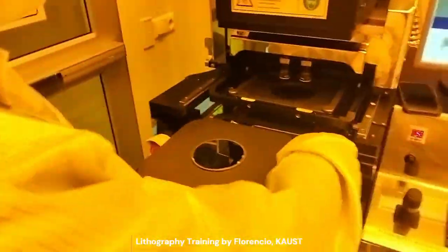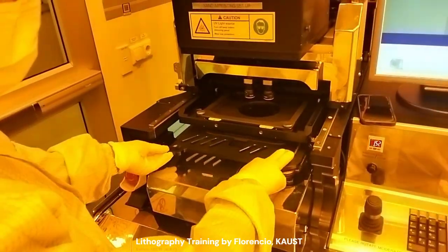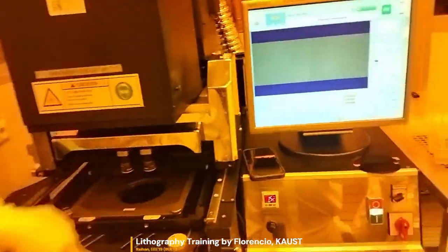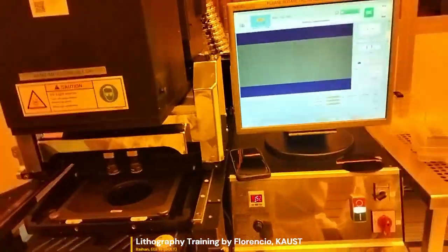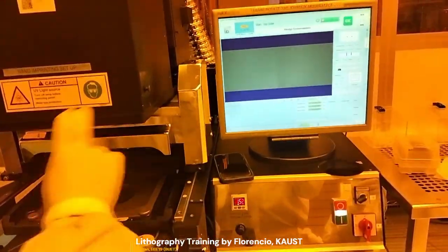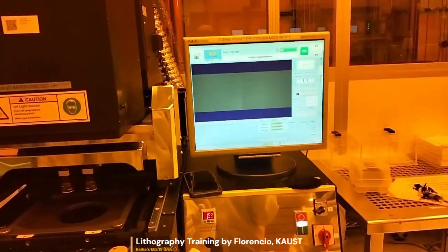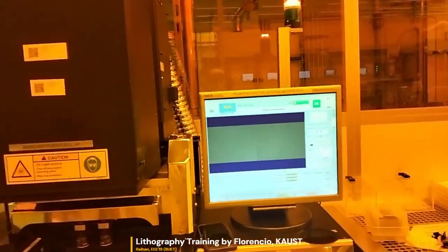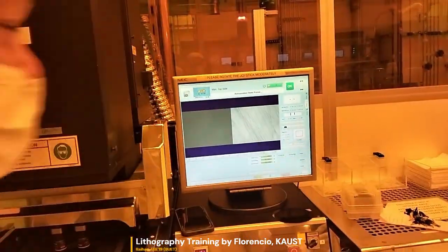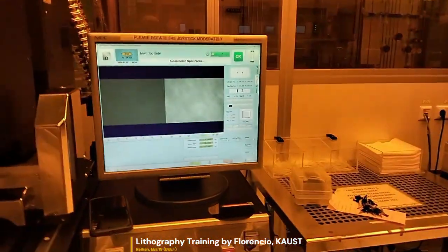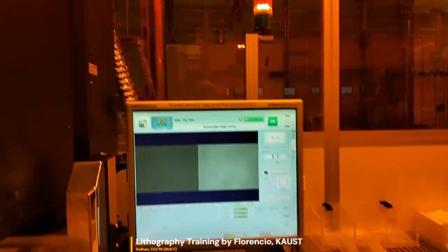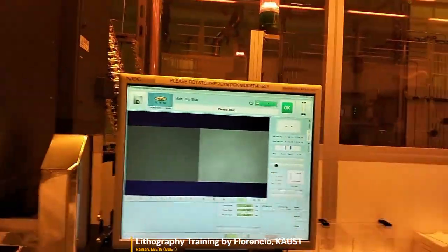Move in my tray. See, the mask will be directly in contact with the wafer. So it's the chrome side that's directly contacting the wafer. At this time, you can align your mask to your wafer sample. But if it's just one layer, all you have to do is center it on stage. One camera is from the bottom chrome layer, and the others will be on top. Okay.